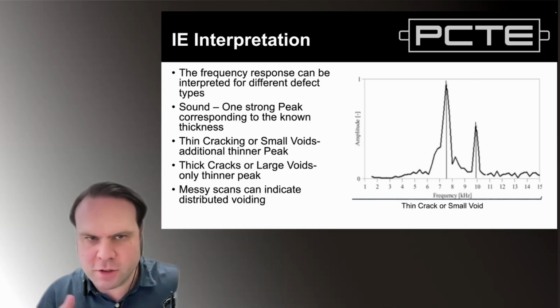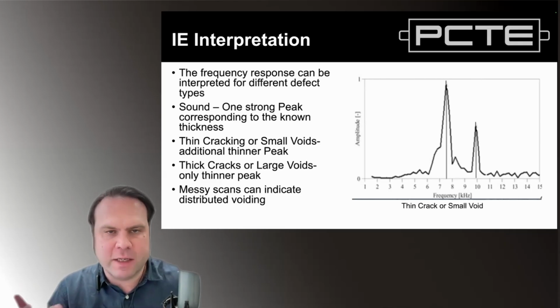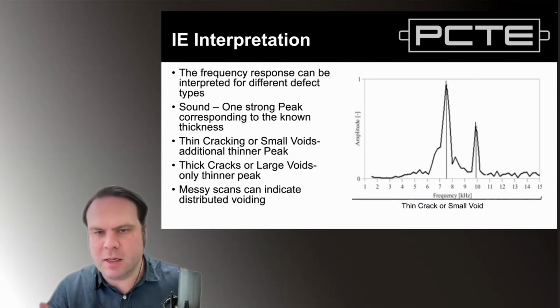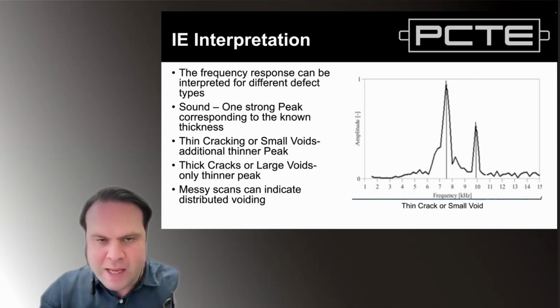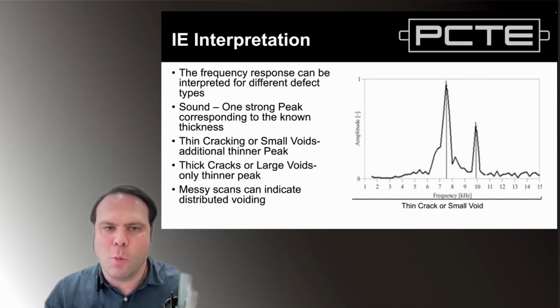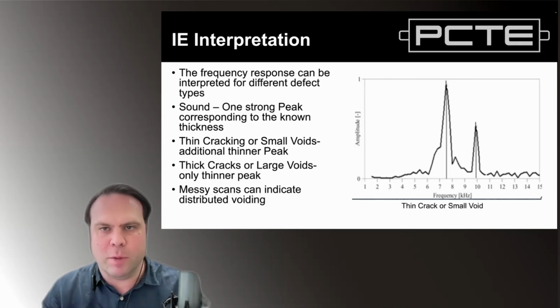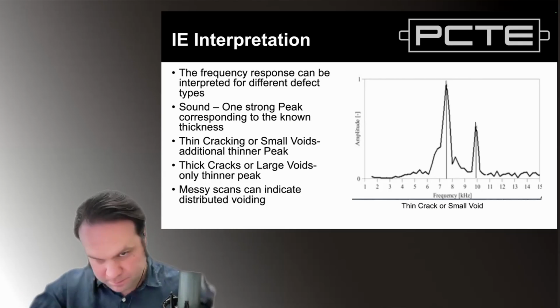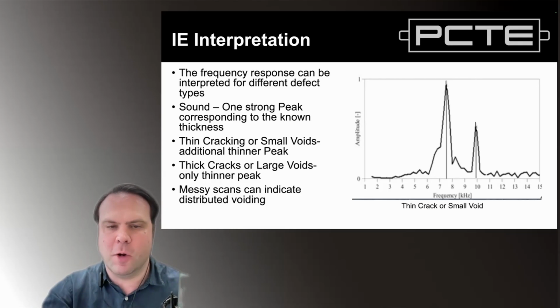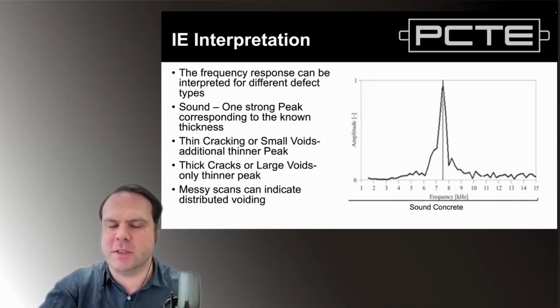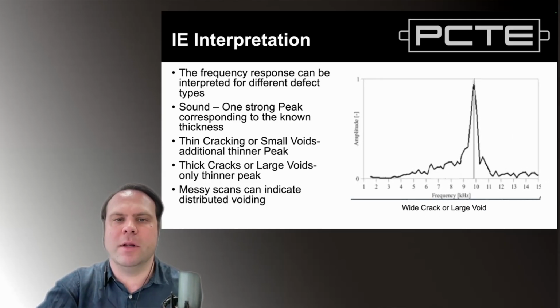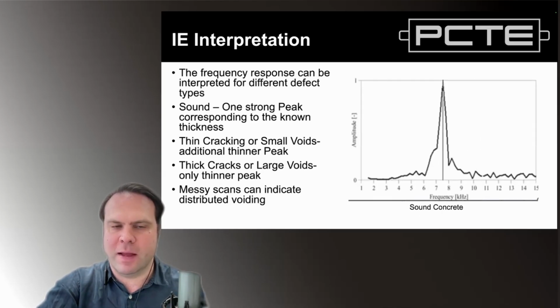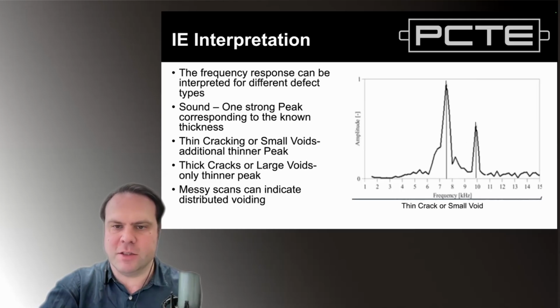Now, if we get into the region of small distributed voiding, one possible output we could get is multiple frequency. This is, I've encountered in real testing, less common, but it's certainly possible if we get voids close to the surface or we get quite disrupted areas, we might ruin our chart, no longer have a dominant frequency measurement we can see. But I'd rather show you some examples of the more typical ways we see frequency shifts, because that's the more common interpretation, is to go from one frequency to another in the regions of defect.